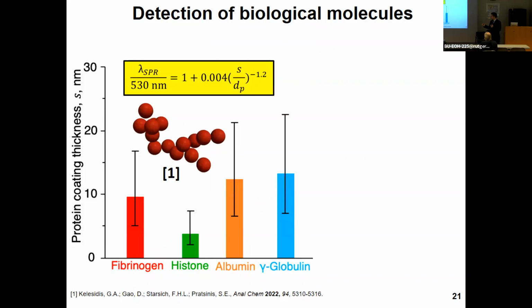And of course, the formation of these clusters changes the optical properties of these nanomaterials, as I showed you earlier. In particular, the position of the light extinction peak changes as a function of the protein coating thickness, based on this relation that I'm showing you over here, and actually that we derived based on the simulations that I showed you before. So by coupling this relation with light extinction measurements in blood containing gold nanoparticles, we are able